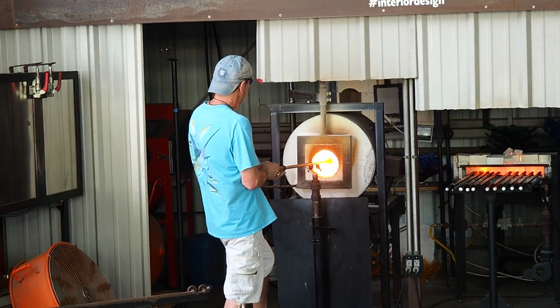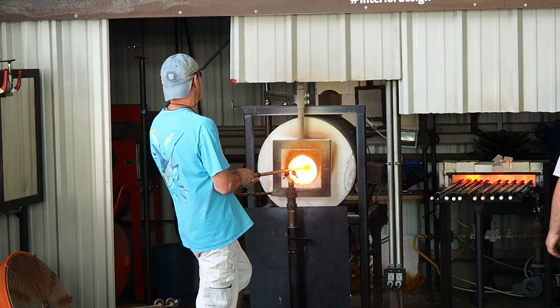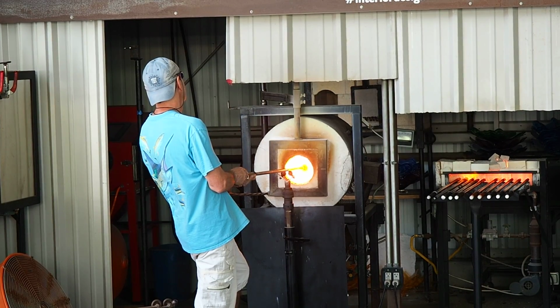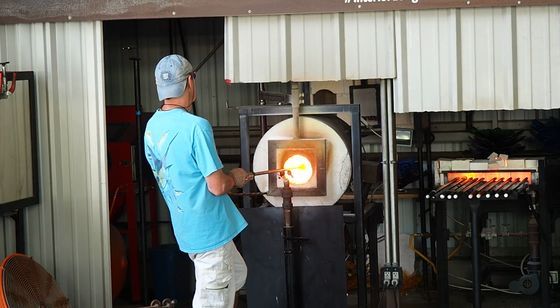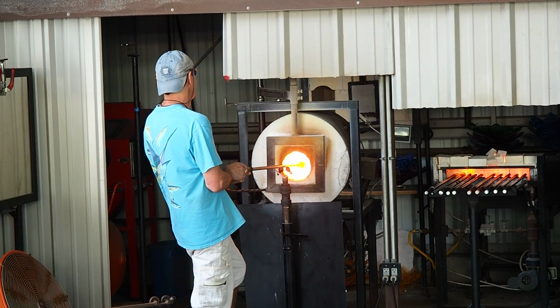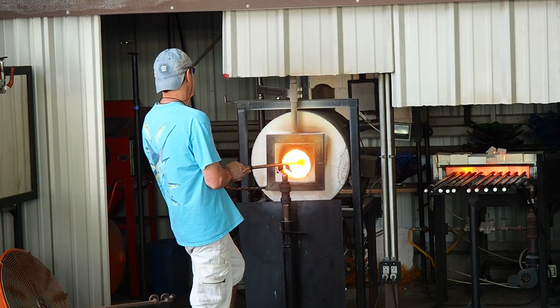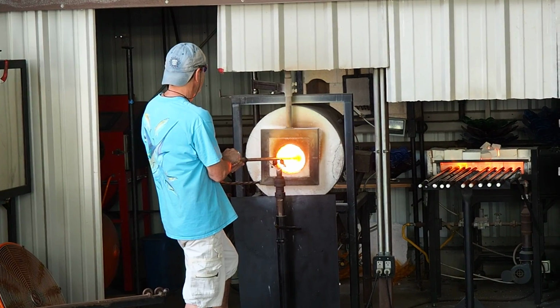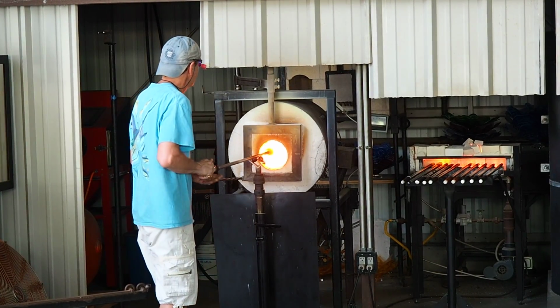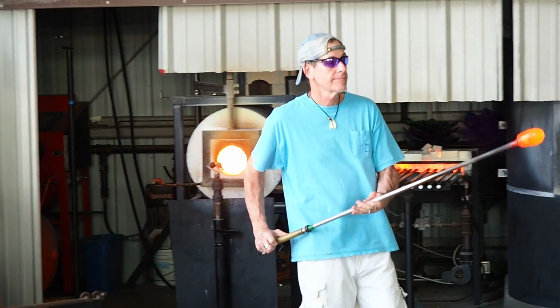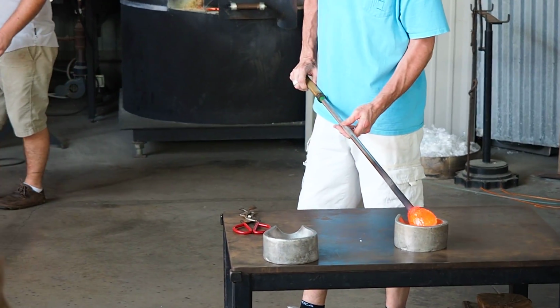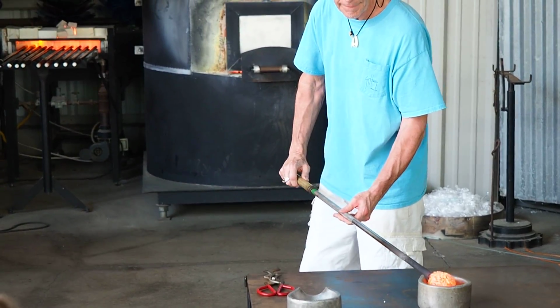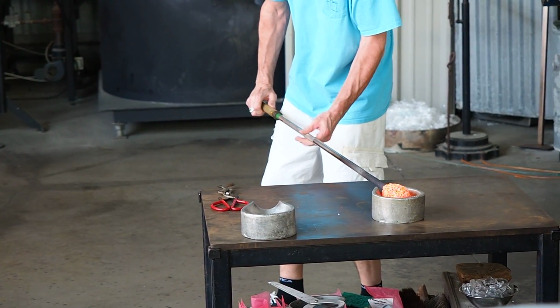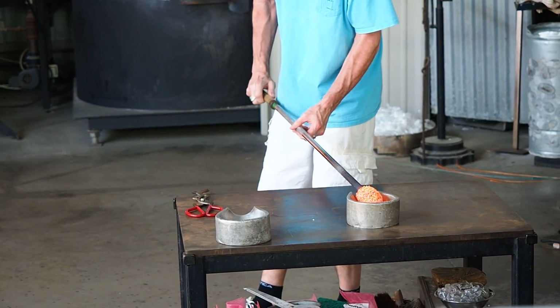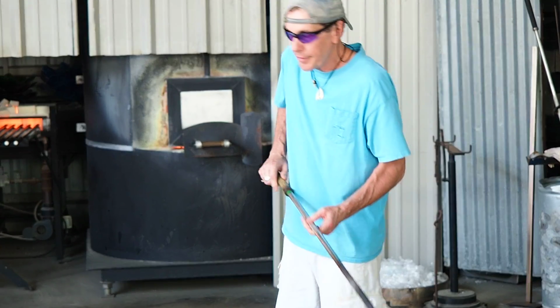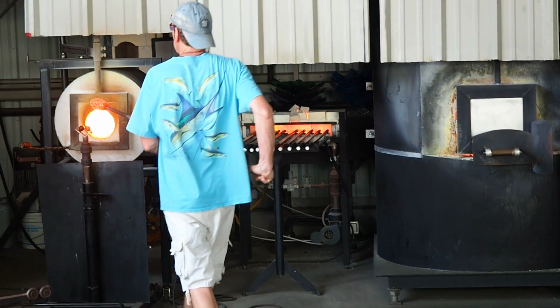In addition of titanium will turn that glass white. In addition of gold will give a whole range of rubies or reds. Cobalt oxide will give you a nice bright blue. Copper oxide, a series of greens, so on and so forth. There's companies out there that add these different metals to the molten glass, and they extrude it, pulverize it into different mesh sizes, and mail it to us. You can see how that pulverized glass sticks right to the outside of that hot gather.